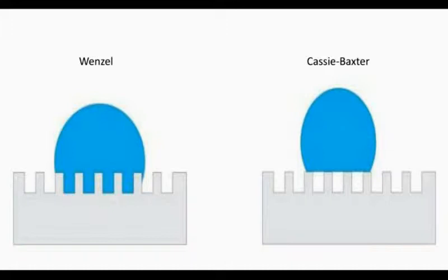Topological factor plays an important role in superhydrophobic surface. The behavior of a water droplet on a nanostructure surface is schematically shown here. Water can either penetrate the asperities or be suspended above the asperities. In either case, much higher contact angles are observed than those observed for a corresponding flat surface.